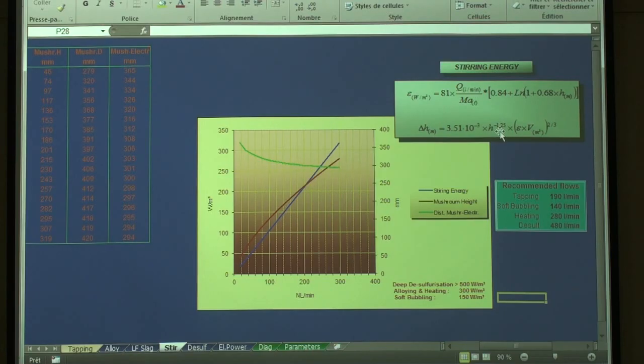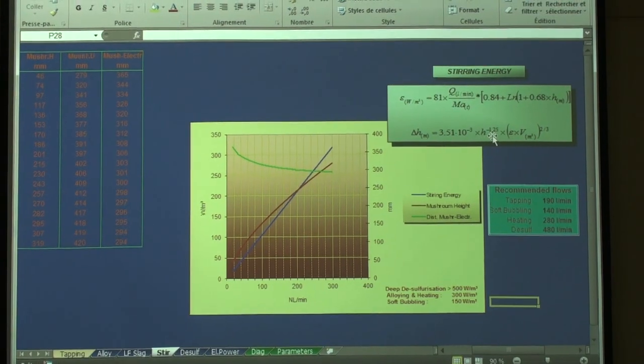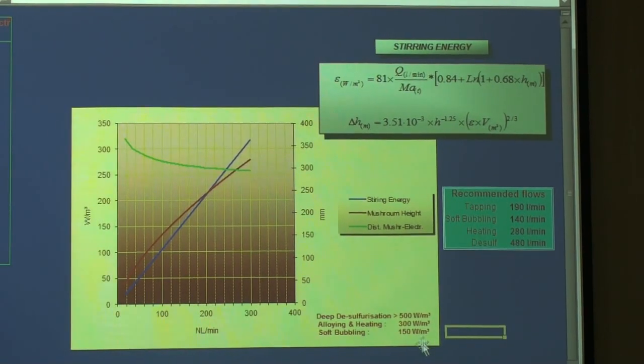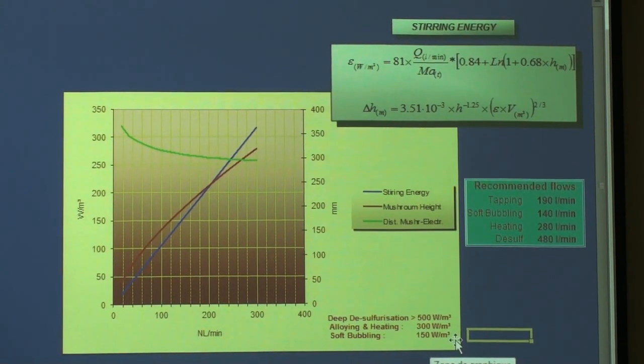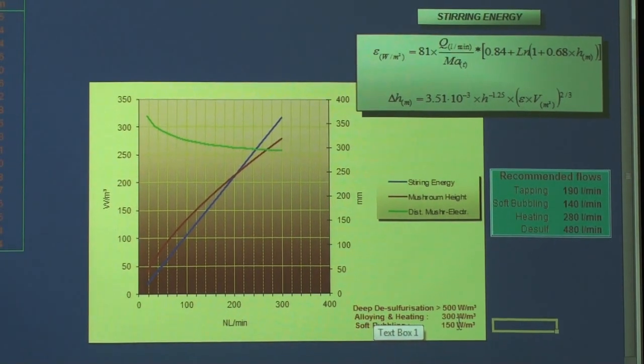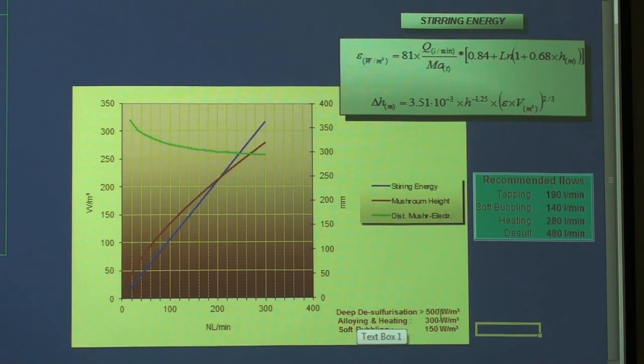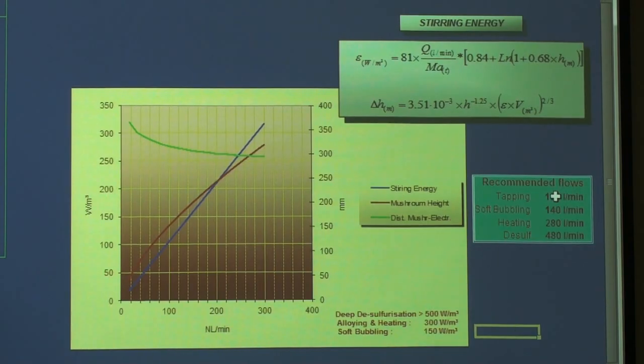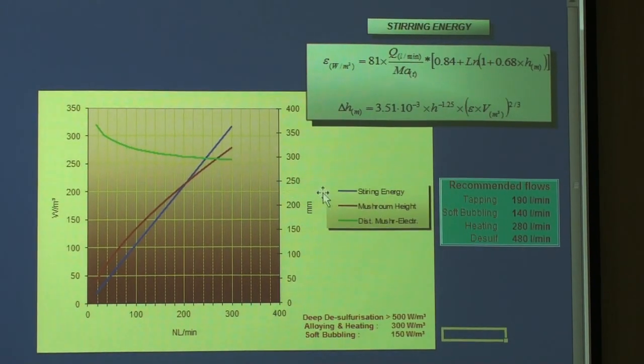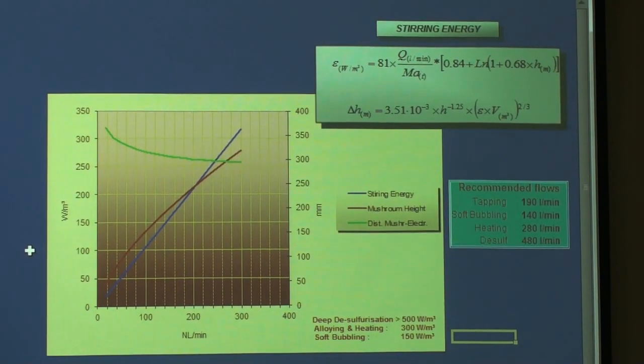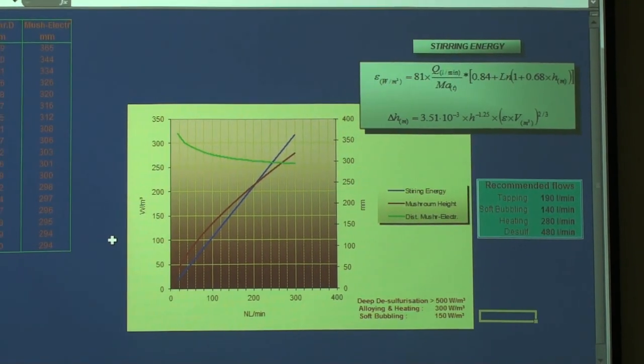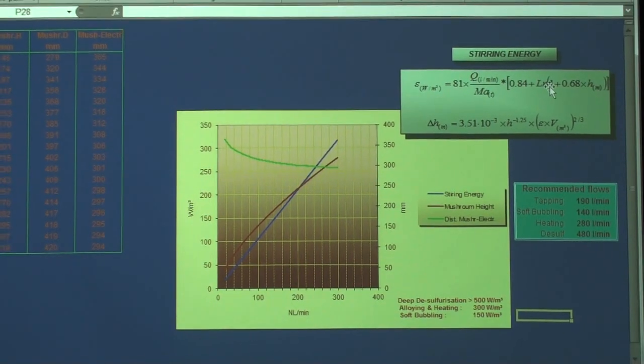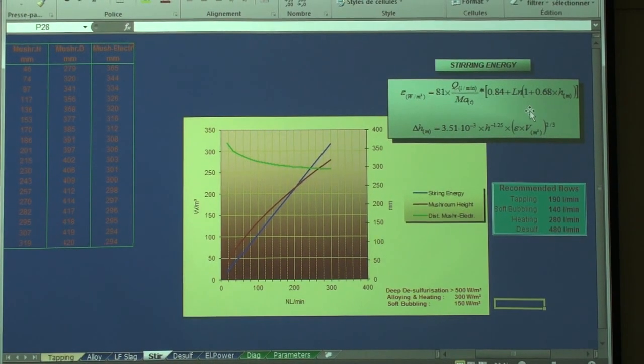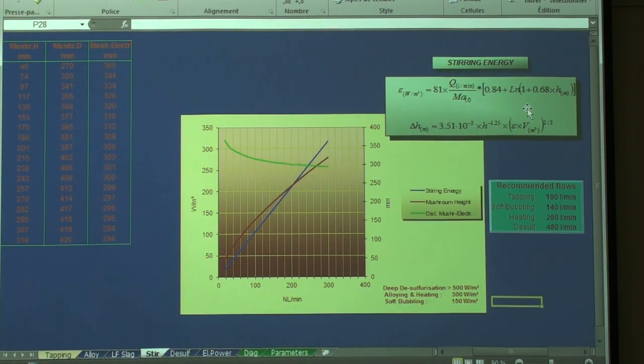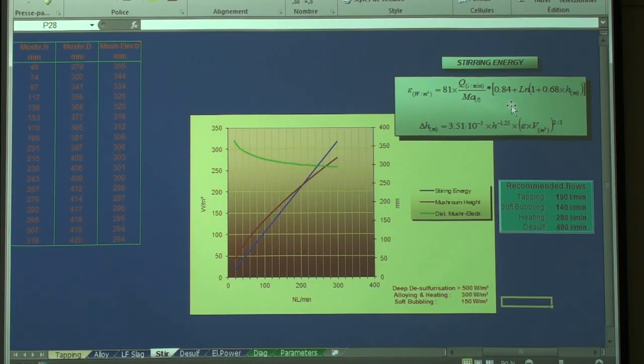So there you have nothing to do because it's already calculated with this criteria for soft bubbling 150 watt per cubic meter, for alloy and heating 300, and for deep desulfurization over 500. So the fluxes are calculated here, depending on the ladle capacity and ladle height and diameter, according to this formula. I have not invented this formula, this is in the literature.